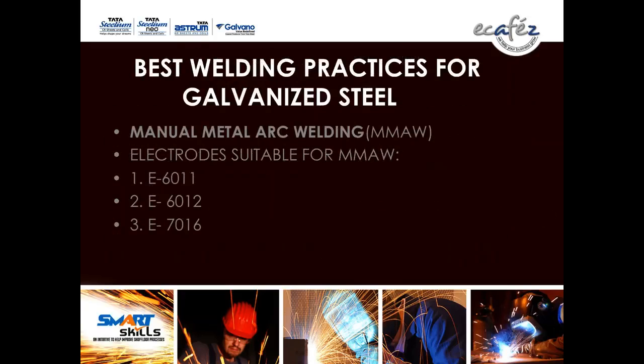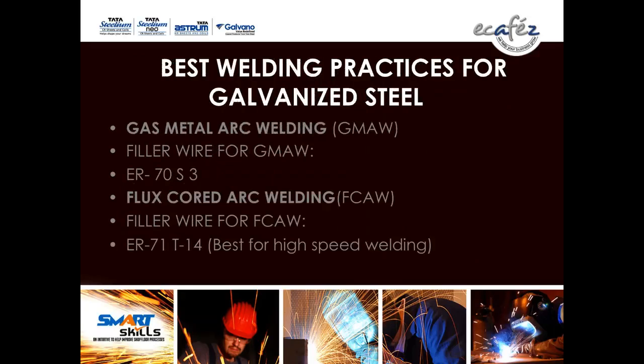Best welding practices for galvanized steel: manual metal arc welding, you can go for E6011, E6012, or E7016. For MIG, you can go for gas metal arc welding with E70S3. Do not use E70S6. You have to use E70S3. And the best results for galvanized steel welding will be given by E71T14. You can weld all your joints using the flux core arc welding process with flux core wire E71T14.